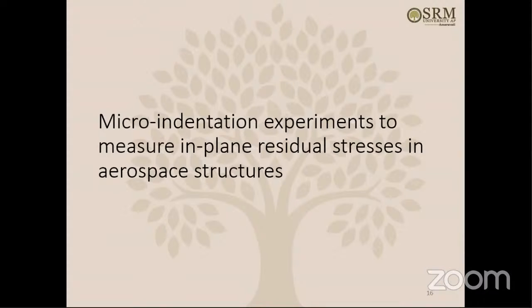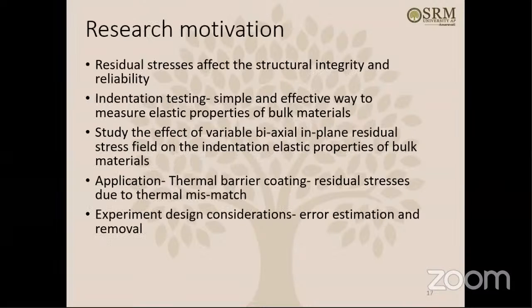In my indentation experiments, on those blade surfaces, because of the thermal barrier coatings and the bulk material below, there is always some thermal mismatch created when it is subjected to very high temperature. Due to the thermal mismatch, there are always some residual stresses. So how do you measure these in-plane residual stresses on those kinds of coated components? We have devised this indentation technique and tried to analyze the effect of these residual stresses. This is what the project is about.